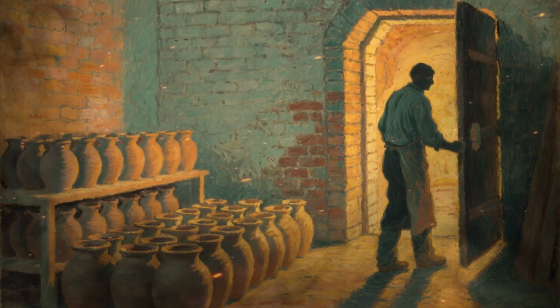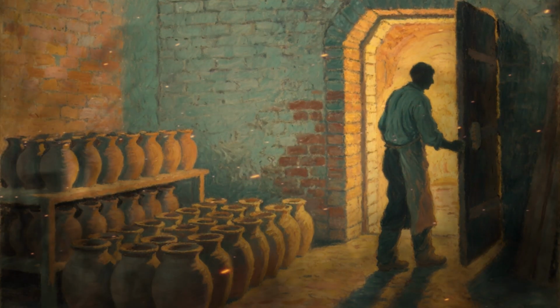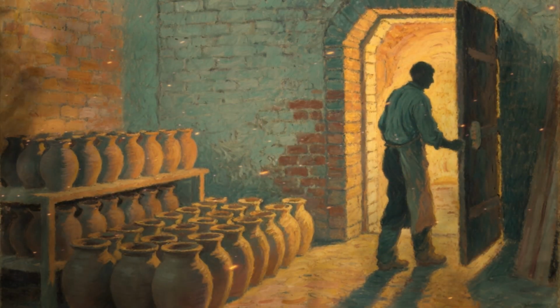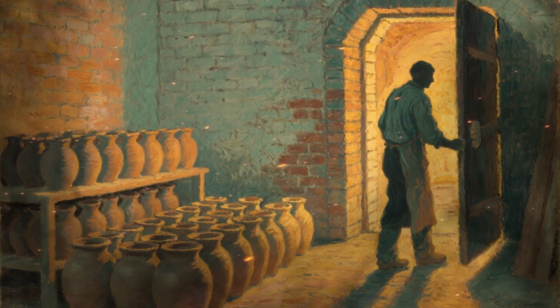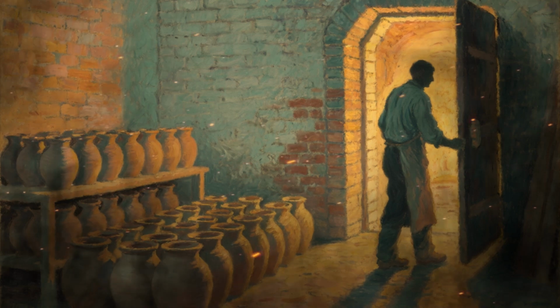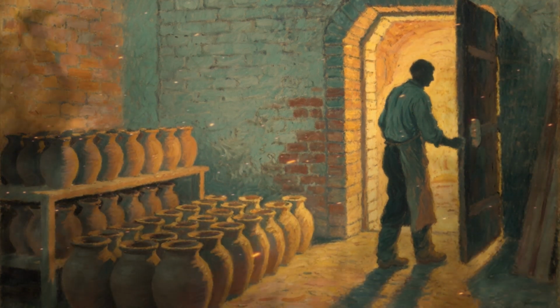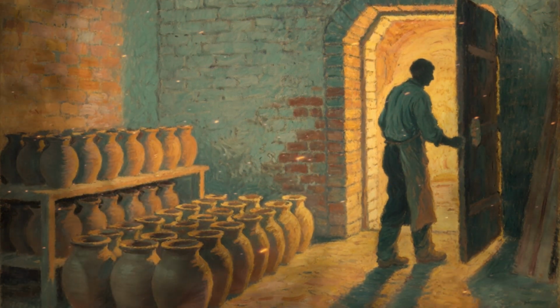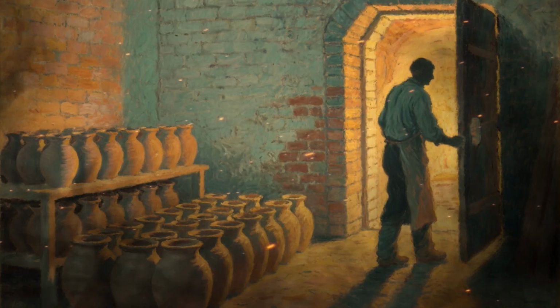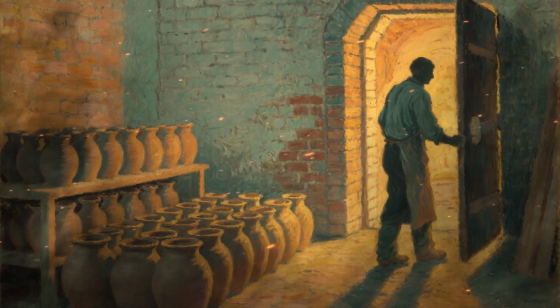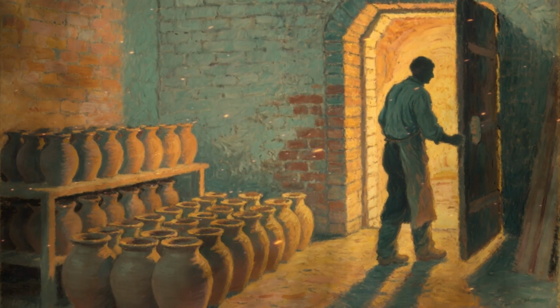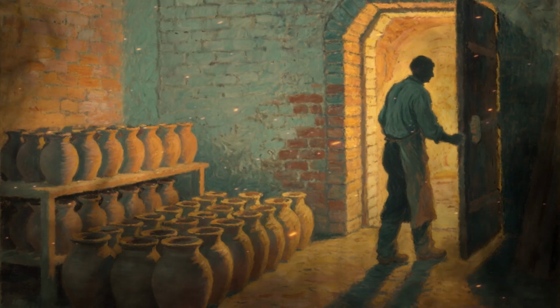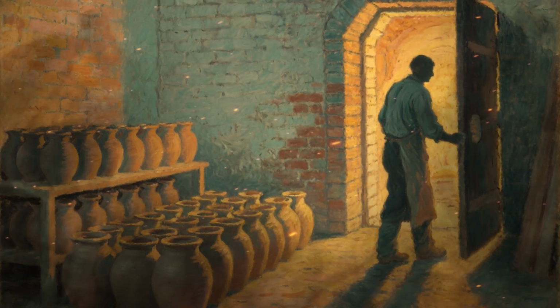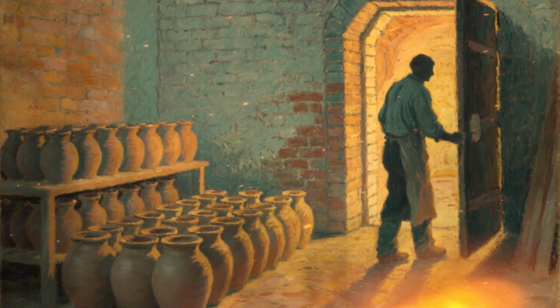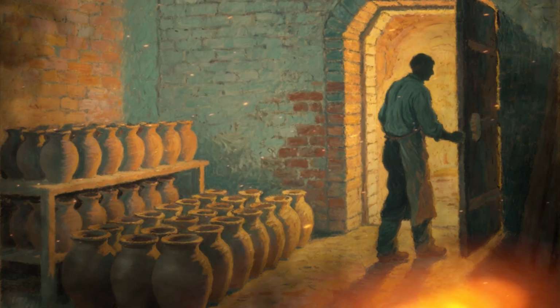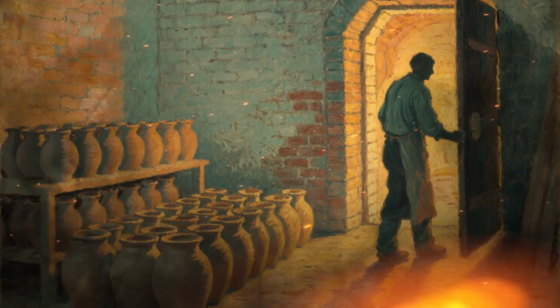With the coming of dawn, the fire is allowed to die. The kiln remains hot for many hours, even after the flames are gone. Slowly, the potter removes the sealed clay door. Heat escapes in gentle waves. Inside, the vessels, now fully fired, sit quietly. Some have cracked, this is expected. Others show minor warping or discoloration where the heat rose unevenly.